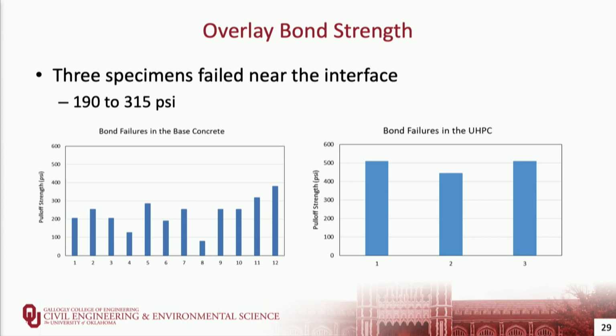In terms of the overlay bond strength, we had just 3 specimens that failed at the interface. 12 out of the 18 specimens actually failed in the base concrete and not the joint between them. And then we had 3 specimens where we missed the overlay thickness, and we actually cored into one of those deeper sections, and so in those cases we were measuring the tension strength of the concrete. But in the cases where we were actually measuring the bond of the interface, they were between 190 and about 315 PSI. The target was just over 200 PSI, and so they were willing to accept these results as meeting their specification.